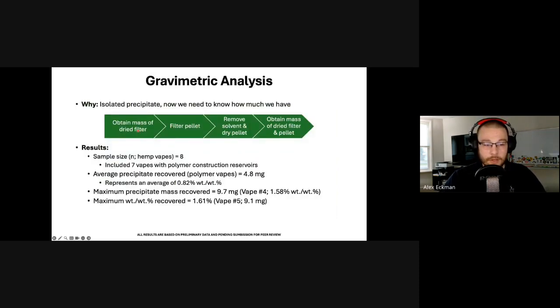Now, with the gravimetric analysis, we obtained the mass of a dried filter. We would then go ahead and filter the pellet out of that centrifuge tube, remove our solvent and dry the pellet, and obtain the mass of the dried filter and pellet after the fact. We had a relatively small sample size.